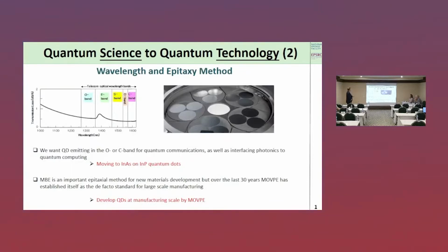So the second aspect of quantum science is, as I said, much of the work that we have done is in gallium arsenide, so that's at 900 nanometers, and a lot of the science has been established at that wavelength. But in fact, for technology, we want to move to longer wavelengths. In particular, we want to use the C band, which is the basis for fiber communications. To move to the C band, we move from gallium arsenide to indium phosphide. But the second thing that we want is, although MBE is a fantastic technique, and we loved MBE, probably over the last 30 years, actually MOVPE has been established now as the industrial standard for mass production of semiconductor materials. So we actually want to develop these high quality quantum dots using MOVPE, and that's what we've been doing. That's what the rest of this talk is about.